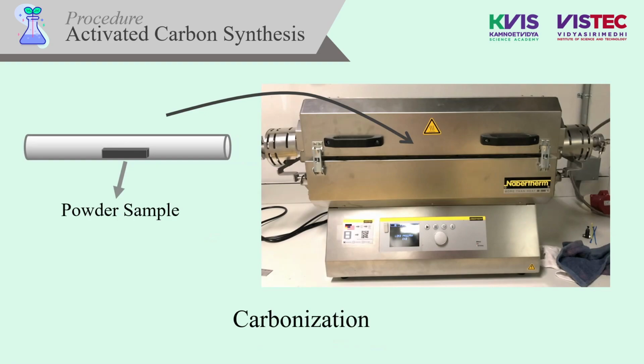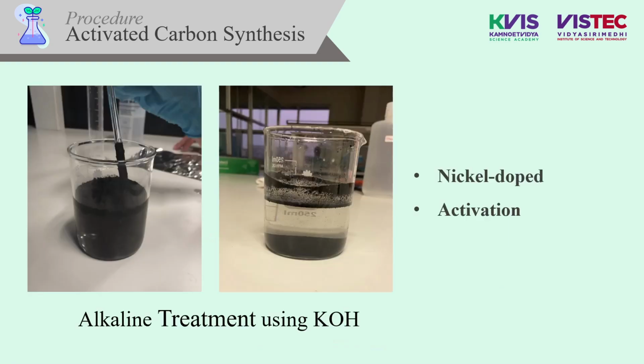This pure carbon black is doped with nickel nitrate, which is a metal that when implanted on the carbon surface will enhance its ability to capture CO2. The doped carbon is activated using potassium hydroxide, and after washing with acid, we will get our resulting electrocatalyst.